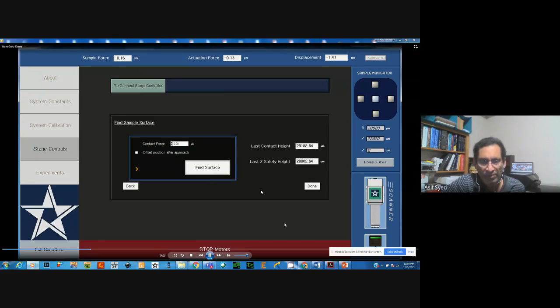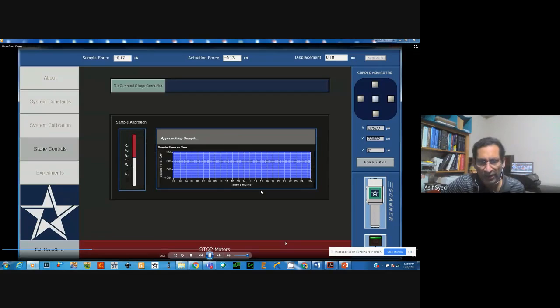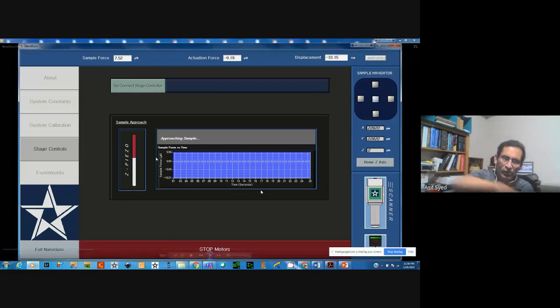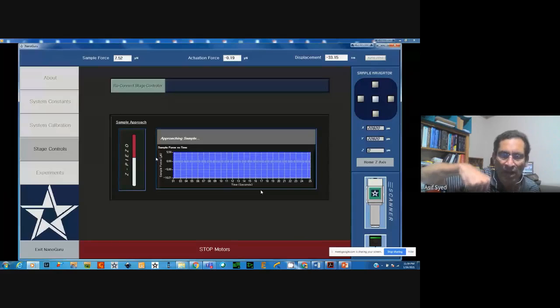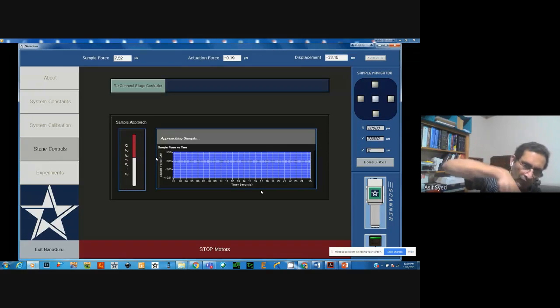So now when you press find sample, you can see there is a window here. In that window, you can see where the piezo is. Right now it is at the middle, but as you want to approach and make contact, we extend the piezo with the transducer, and with the extended position, we approach the sample surface. The idea is that when the piezo is extended and the tip makes contact, we can pull the piezo back quickly so that it can be away from the surface, or make contact with the required force that we need. That is why we extend the piezo and approach the sample surface slowly. As soon as the tip makes contact, the piezo immediately will pull the transducer away from the surface. That you can see here.